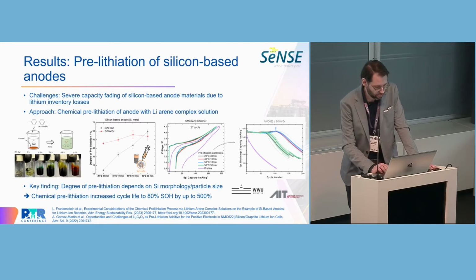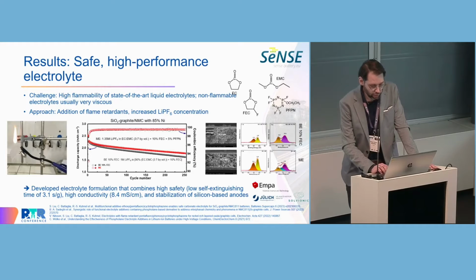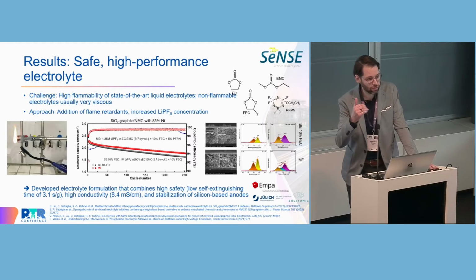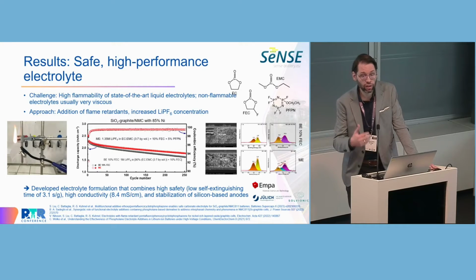out quite well. Then we also worked on the electrolyte, and here we gave ourselves another challenge. So we didn't only want to stabilize the cell chemistry, but we also wanted to render the electrolyte non-flammable. But because this call was asking for fast charging capability, we couldn't really go for some of the alternative liquid electrolytes, for example, based on ionic liquids, which are quite viscous and typically have a significantly lower lithium-ion conductivity, and then it's difficult to reach the project targets.